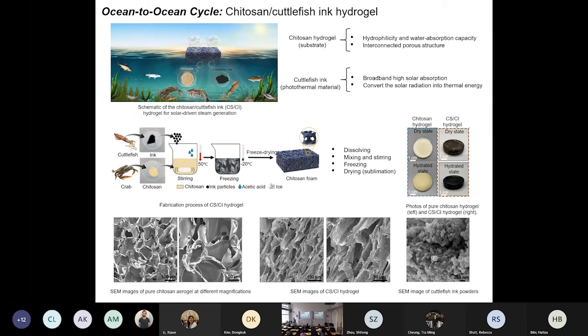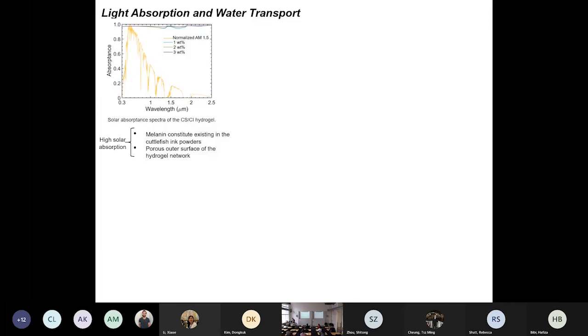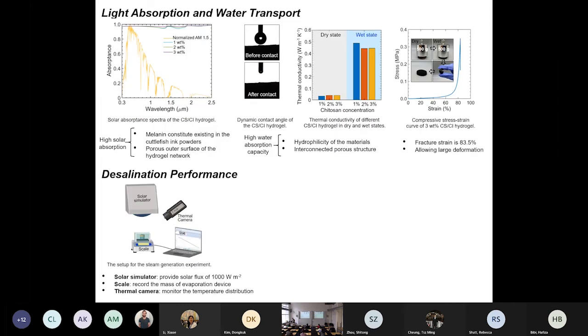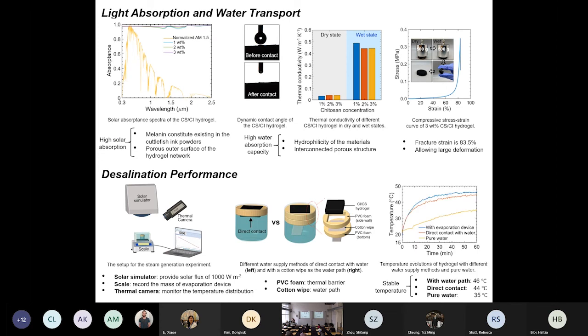This material itself is extremely absorbent to water. And we also ran the mechanical test and the desalination test. We have the solar simulator in our lab, and also a digital scale to monitor the change in mass, and we record the temperature up to 90 minutes. And then we only take the stable data from 30 to 90 minutes, and the temperature we measure.